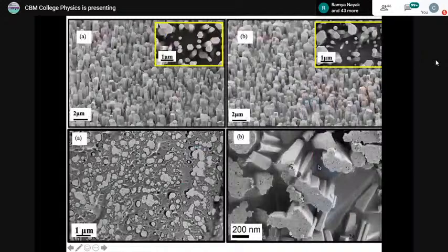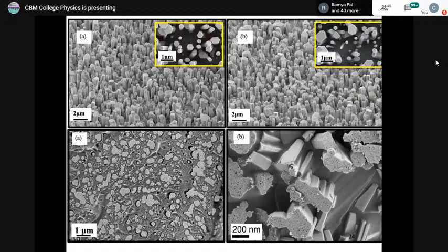Not only that, we can do the same thing on silicon platform and also on quartz platform without any issues. So we take quartz, we put let's say boron nitride layer on top of it, and then put aluminum nitride seeding layer, and we start gallium nitride growth as normal, where we have 2D, and we get nanorods here also without any issues. And also very important thing is that we can lift it off without any problem.